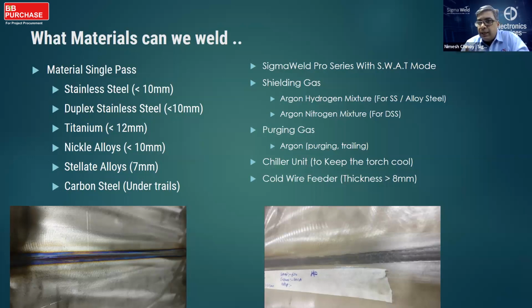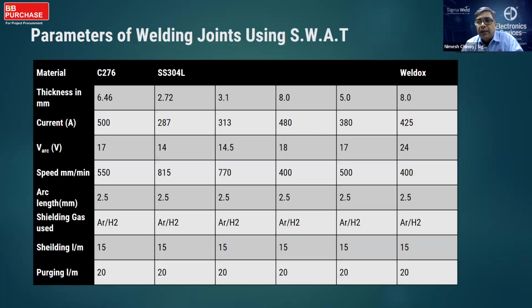What you will need is Pro Series equipment from Sigma Weld with a SWAT mode on it. You need to choose the gas: argon-hydrogen mixture for stainless steel or alloy steel, argon-nitrogen mixture for duplex stainless steel or super duplex. Purging gas can be argon altogether. You can use a chiller unit to keep the torch cool if you're welding longer seams together. And if you're welding more than 8 mm thickness, we'll use a cold wire feeder to add a little bit of wire to take care of the undercut or underfill.